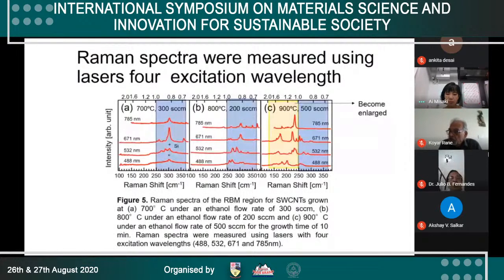Raman spectra of SWCNTs grown at 700, 800, and 900 degrees C under the optimum ethanol flow rate for each growth temperature. When the growth temperature was 700 degrees C and 800 degrees C, RBM peaks were observed in a similar region. But at 900 degrees C, the RBM peak was observed over 250 Kaiser. This shows the diameter increases at 900 degrees C.